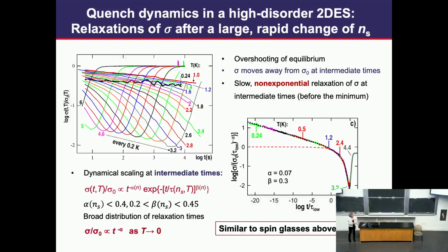I think it's interesting that exactly the same kind of time dependence was found in spin glasses above the spin glass transition temperature. So this is what happens immediately after, at intermediate times.